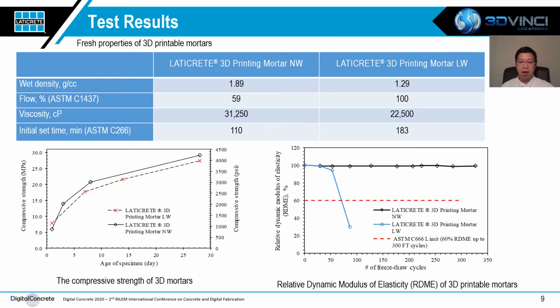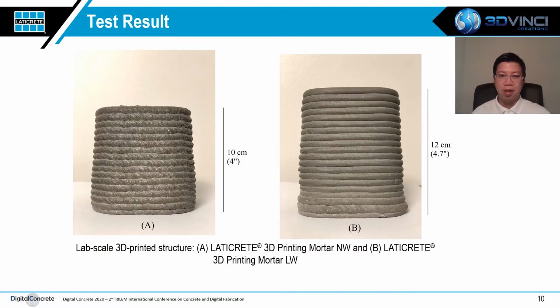The lightweight material, however, did not survive the freeze-thaw test, which indicates this material is not suitable to be used in areas where winter exists. In addition to those tests, we assess the printability of our materials by conducting lab-scale printing using a desktop 3D printer that we modified. As the results show, both lightweight and normal weight materials are printable.